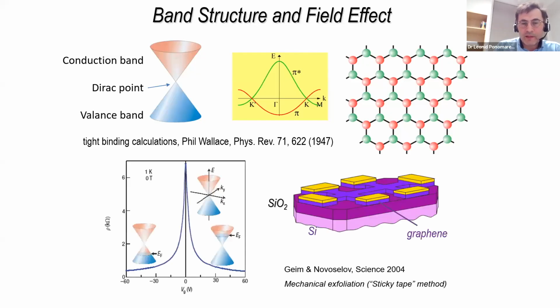Okay, so what Geim and Novoselov did in 2004, is that they not only isolated graphene, but they also placed the film of graphene on a silicon wafer, as schematically shown on the bottom right image. So here you see silicon, an oxidized silicon wafer. Silicon is a conducting material, silicon oxide is an insulator. So they prepared exfoliated graphene on top of it and added some gold contacts to it. And they were able to study the resistance or resistivity of graphene and study how this resistivity changes with applied voltage between graphene and silicon substrate.